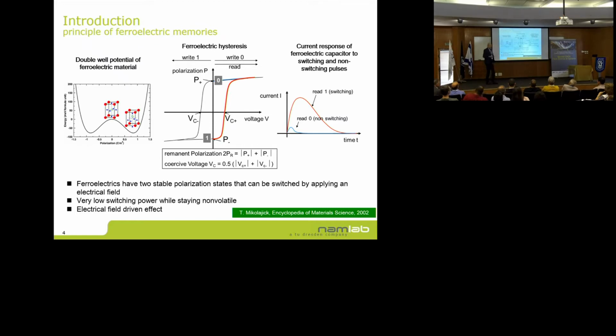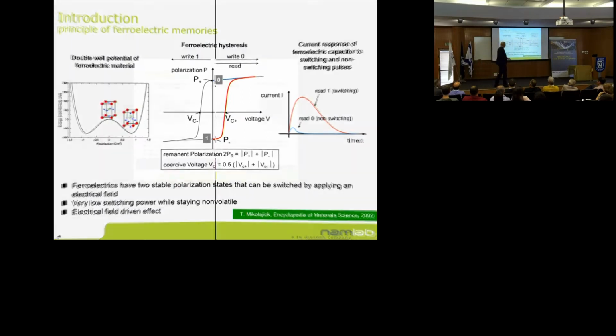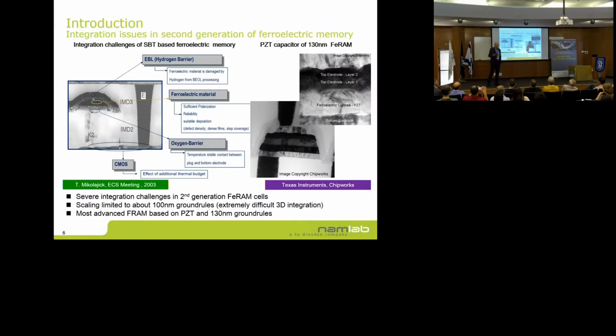Moreover, since you are really sensing the charge that is coming out during switching, during scaling you have to maintain this charge, and you would have to go to the third dimension, like in DRAM, to maintain enough charge if you go below 100 nanometers. And this is virtually impossible with PZT or SBT, because on the sidewalls of such a trench or stacked structures, you typically get the pyrochlore phase, and this is non-ferroelectric.